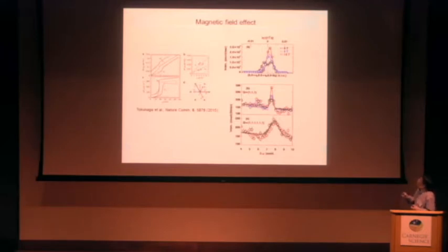After this magnetic field is applied, the exact spin structure is not clearly known because it's hard to measure single crystal diffraction at this high field. But what we know is there is a huge enhancement of polarization going along the 111 direction when you apply a big field like this. So what happens here if we measure this phonon resonance under a big field? Here's the magnetic Bragg peak, showing that the magnetic structure has been affected by the field. Exactly what it is, we don't know for now.